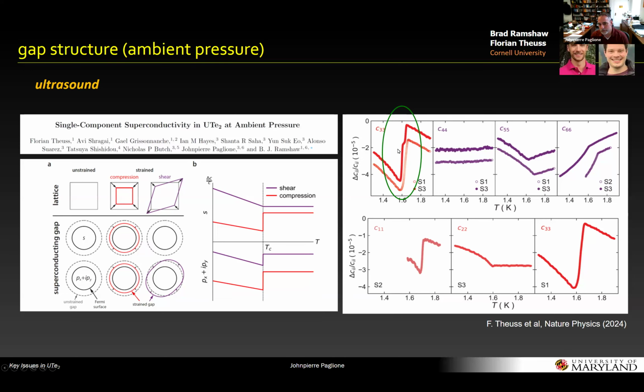So the question was, if you compare these samples, was there a jump in the shear elastic constants or not in either of the samples, which would indicate whether you had a multi-component order parameter. And you can see, right here, here's the data. Here's the shear elastic constants, and there doesn't seem to be any jump in either sample. There's kinks in C55 and C66, but there's no jump. So that led us to conclude that the order parameter, at least in zero field at ambient pressure, is a single component order parameter. Now, interestingly, C44 shows nothing through this transition.